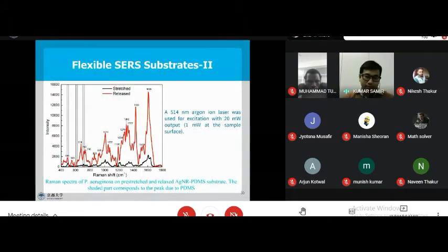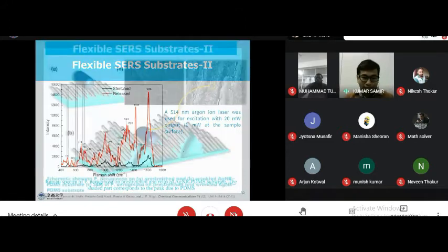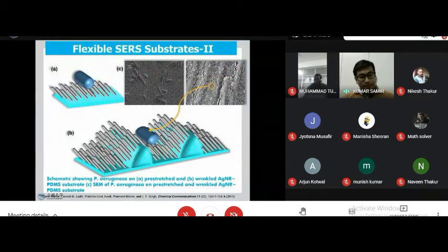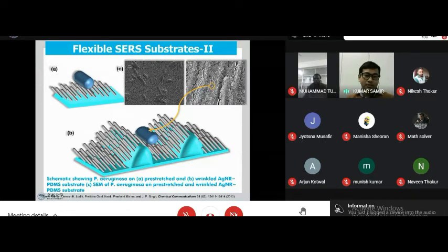So this shows the SERS signal for the bacteria before and after releasing the stress, and we can clearly see that there is around 11 times enhancement in the SERS signal of the bacteria. We can explain it like this. When the bacteria is on a planar substrate, only the nanorod tips, which are the hot spots, or you can say the positions for maximum enhancement for SERS, are touching the bacteria, and only from the bottom part.